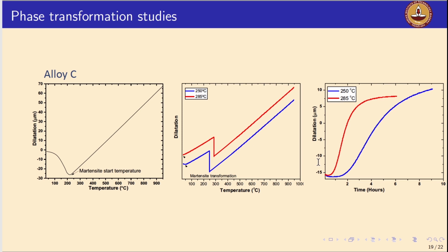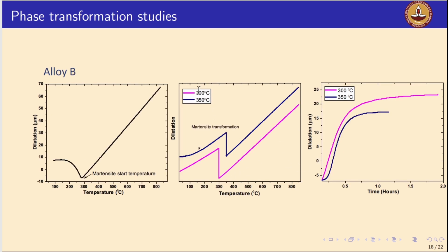So with these three exercises, we can already see how we can optimize the weld thermal cycle, isn't it? Right. Apart from optimizing chemistry, with the hot cracking susceptibility studies, we can identify which chemistry can give us a microstructure without martensite, and the bainitic holding temperature and time such that it can be practically used in the welding studies, right? Based on these studies, we can already identify that for alloy B, the weld thermal cycle of 300 degrees centigrade bainitic holding is ideal to get a good carbide-free bainite containing microstructure, right? So we have already optimized this chemistry based on the hot cracking susceptibility studies.